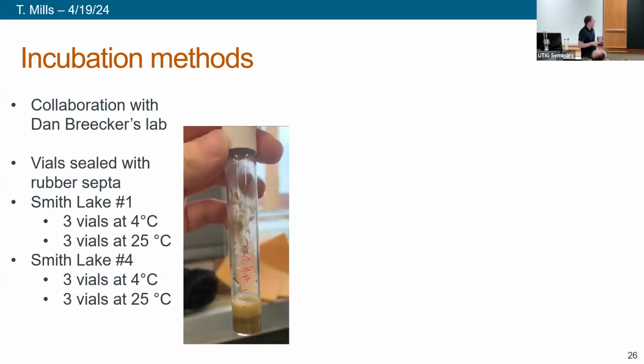And so this is how we're performing these incubations, and we're doing this in collaboration with Dan Breecker's lab, and he's helped us quite a bit with how to do the incubations and being able to measure the headspace gases from our incubations. So essentially, we start out with a glass vial and a lid that has a rubber septa on it at the top where you can poke a needle through that piece of rubber, and when you remove it, it still stays sealed.